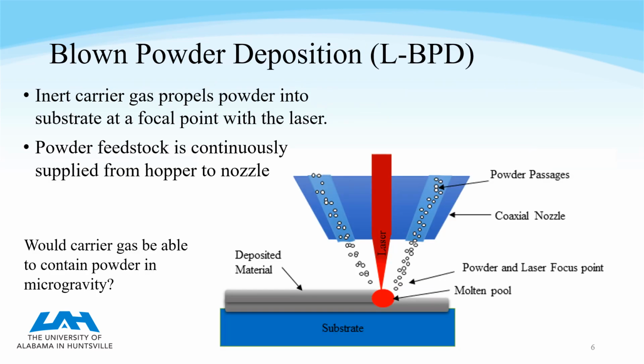The other method we're looking at is laser blown powder deposition. Whereas powder bed fusion rotates through the different stages, blown powder does it all at once. So you have this gas that's depositing the powder, and at the same time you're melting it with a laser, and as you're moving along, the material behind it is cooling and solidifying. So between the fact that the powder is moved by gas rather than gravity, and it's melting and, more importantly, sticking as it's hitting the substrate, we think that this method will also be viable in space because it seems that it relies very little on gravity. While of course we don't know in practice, in theory this will work.